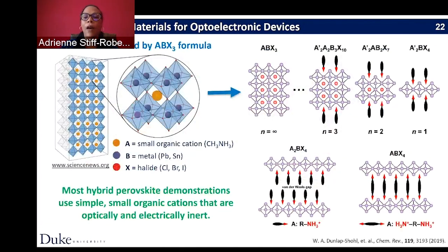And so this is what's really interesting about work I'm doing now related to hybrid perovskites. Hybrid perovskites have a lot of interest because they've demonstrated very high power conversion efficiencies as solar cells. But the really cool thing about them is that they're a hybrid material. They have an inorganic framework made up of metal halides that are represented by these octahedra. And within the space of these corner-sharing octahedra, there is an organic molecule. And this is a crystalline structure, so you know exactly where all the different components are. You can predict what the properties will be, you can control those properties, and you have the process-structure-property relationships that you need to really advance a particular technology.